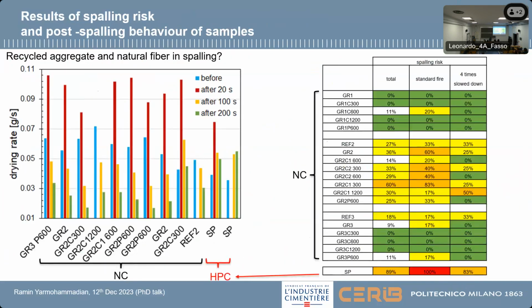So again, we tested many concrete samples with recycled aggregate, with cellulosic fiber, with PP fiber. And also we compared all of those with high-performance concrete, since high-performance concrete is much more sensitive than the normal one. So what is the difference between the high-performance concrete and normal concrete?